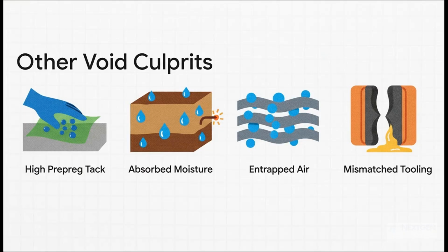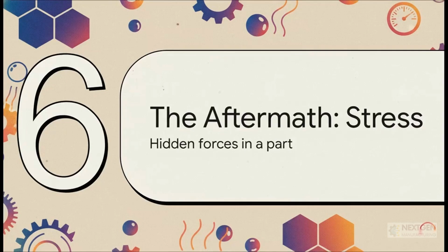And the crazy thing is, this battle starts long before that autoclave door ever closes. If the raw material is too sticky, it can trap air as you're laying it up. If it's absorbed moisture from the air in the room, well, that water is basically a ticking time bomb. Even the tool the part is built on has to be perfect, otherwise it can create little gaps for the resin to escape through. Okay, so let's say you do everything right.